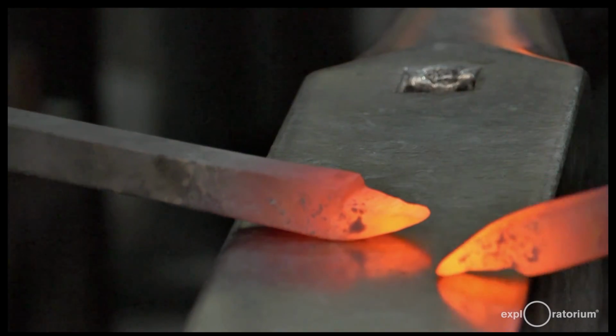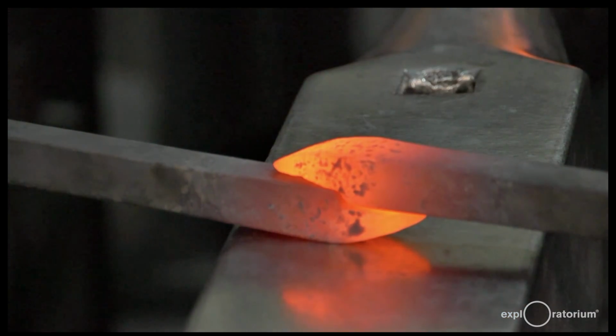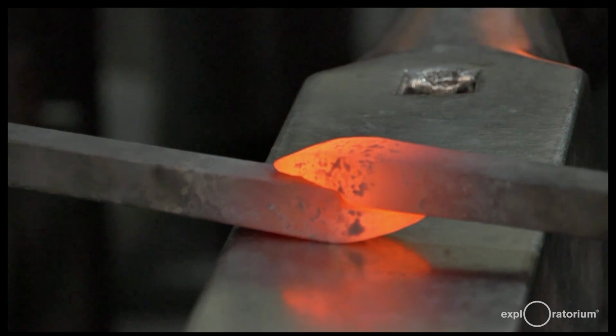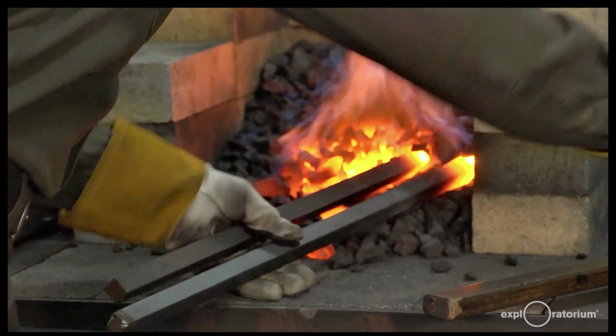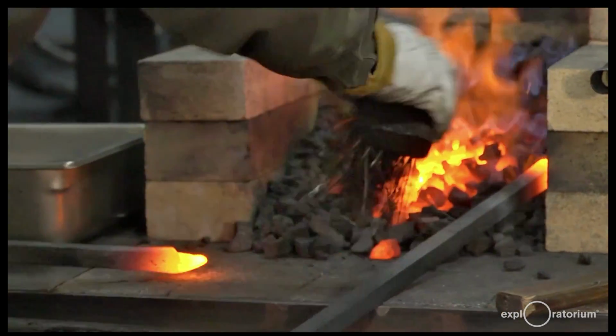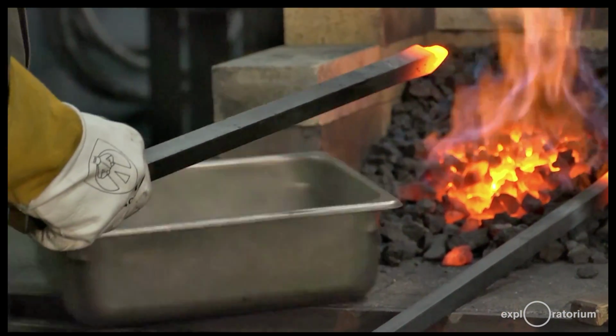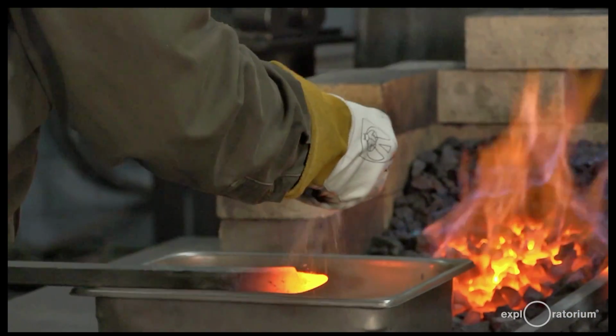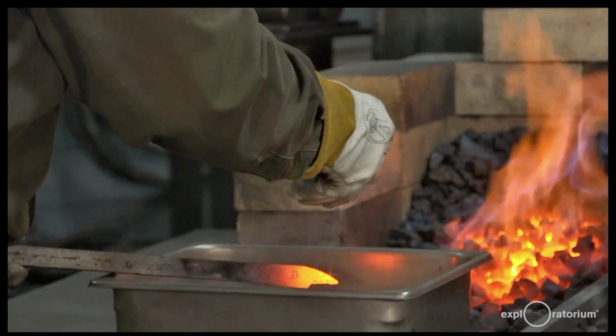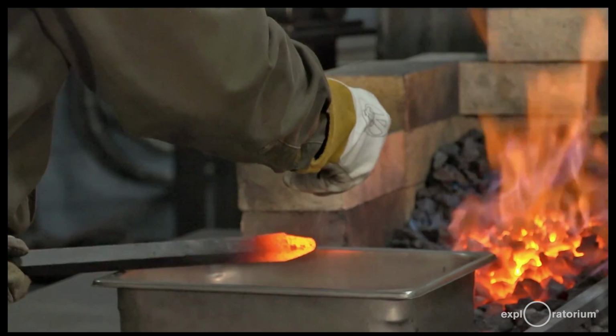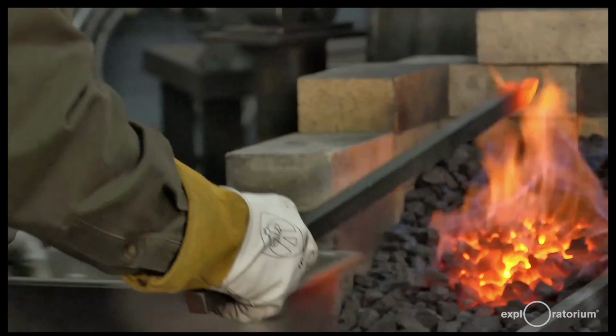So 2 equal pieces mate together like this during the weld. But they have to be a lot hotter than that. This is the step where I put borax on them. Take a little bit of the iron oxide with a brush there. This is a little better than 20 Mule Team here. It's anhydrous, like industrial borax.